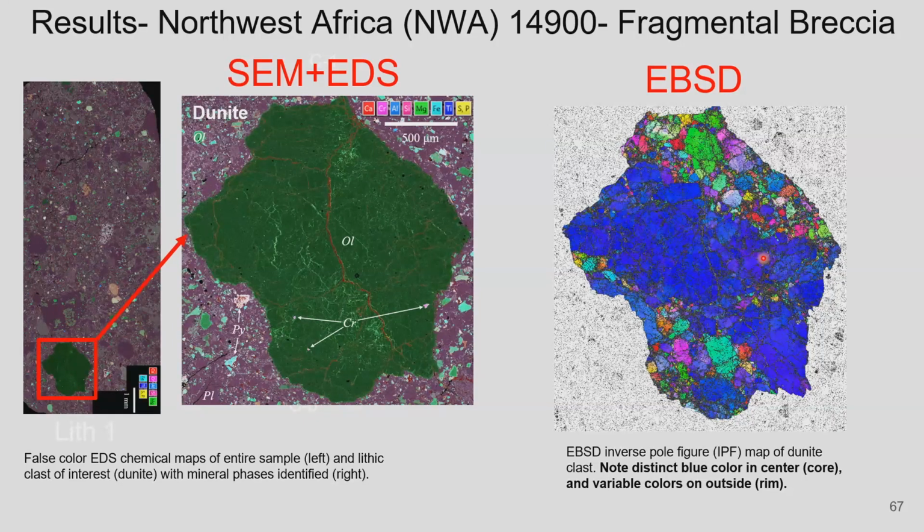The second idea, which I'm still trying to wrap my head around, is this: say you start with one olivine grain, and the olivine grain gets hit by an impact and gets deformed. You have bending along certain parts of the grain, where parts of the grain are displaced, misoriented, and bent. They can give a difference in crystallographic orientation from the part of the grain that wasn't bent as much. So those are two ways you can form this map. We're still trying to find out which way seems plausible, but we're probably going to say both are plausible in our future work on this.